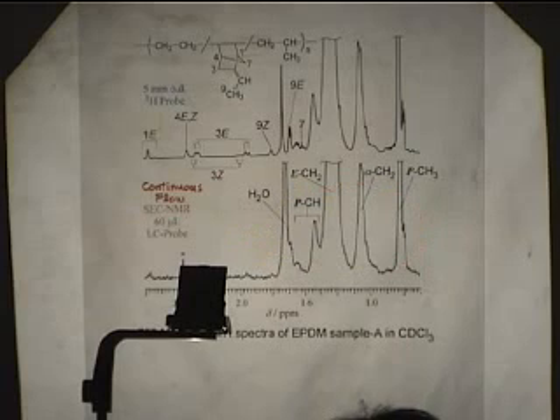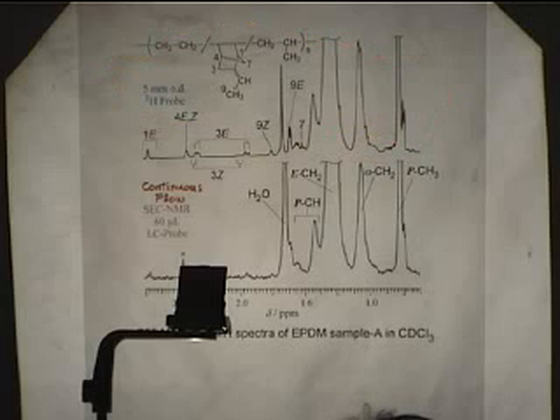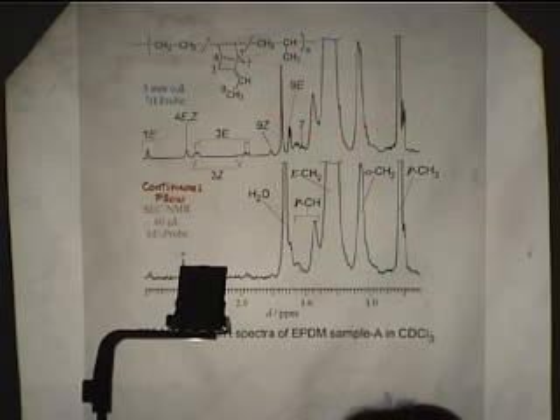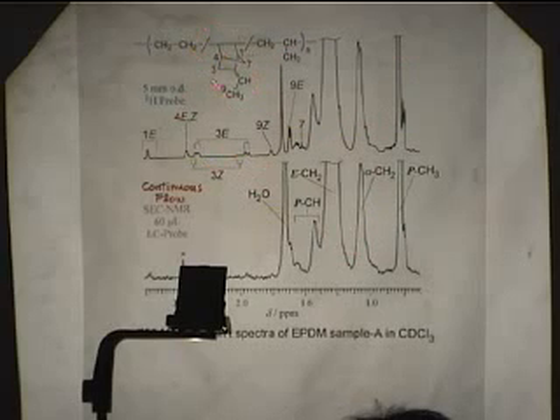This is a spectrum measured under the conditions mentioned above. As you see here, the signals due to methyl and methylene both have high signal-to-noise ratio, almost comparable with that obtained by the normal procedure. However, small resonances due to a small amount of diene are too weak to be detected under continuous flow mode. So, in order to determine a small amount of diene,